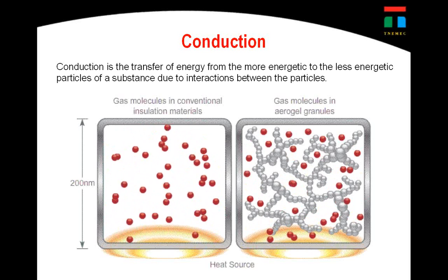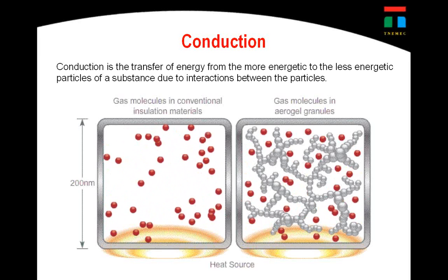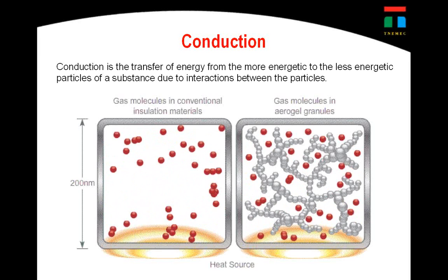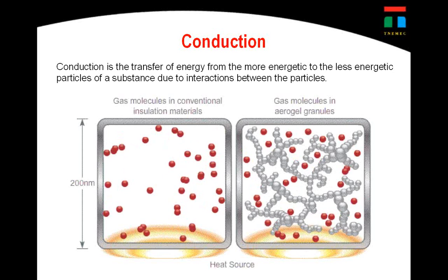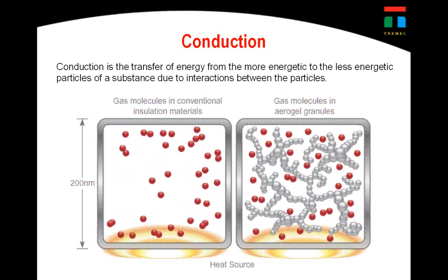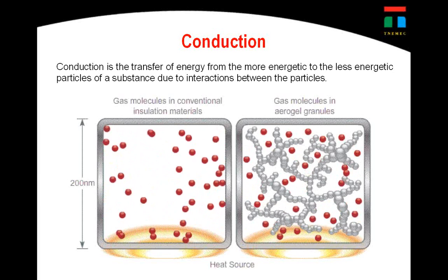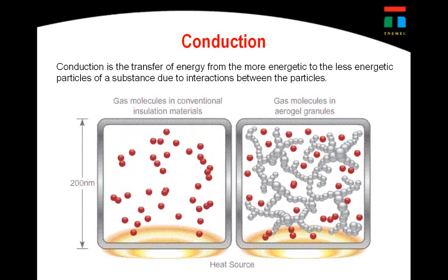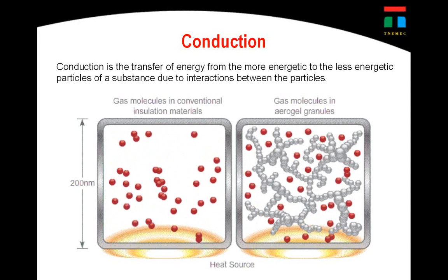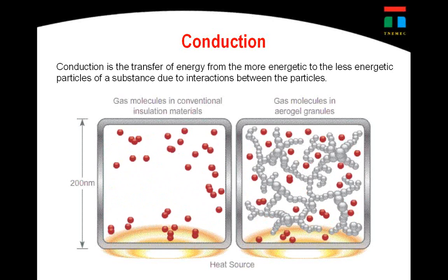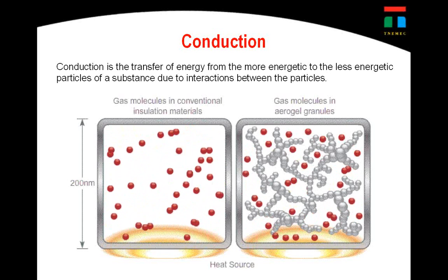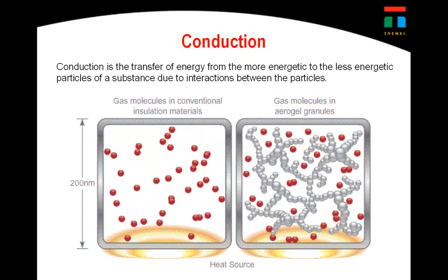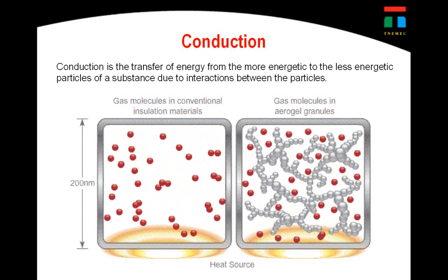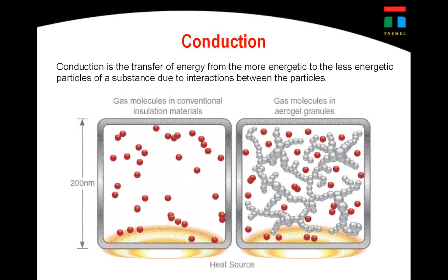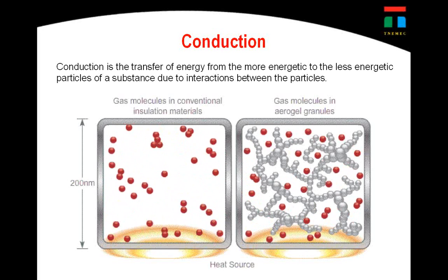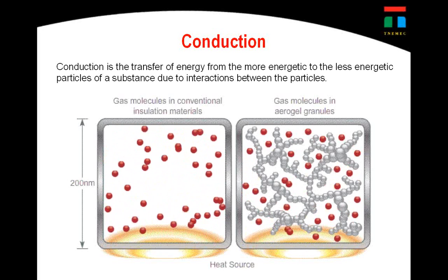So you can see if I were using this in a thermal break condition and I had a cold steel temperature, let's say at minus 20, and I was trying to slow the migration of temperature, by the time I get to the very top of the film, the amount of air movement or air temperature in a room would be so slow that you'd be almost within the dew point, not within the dew point, so that you never form condensation. And that's where this comes into the reduction of heat and cold, is slowing these molecule transfers down.